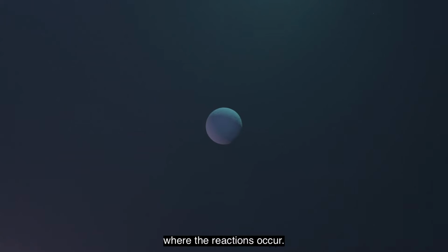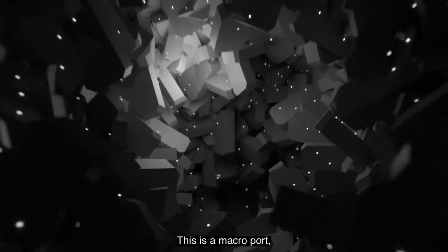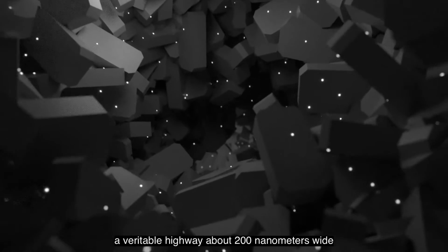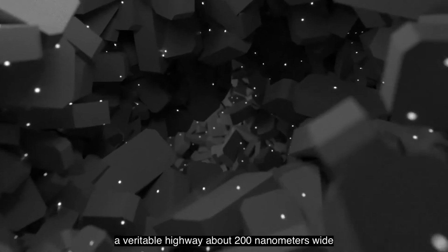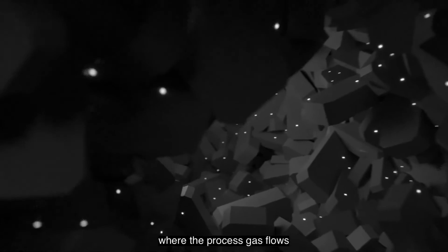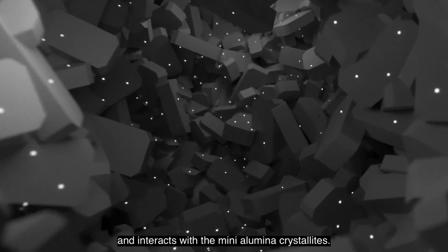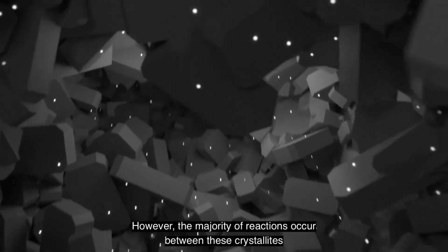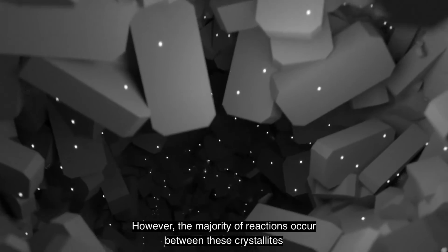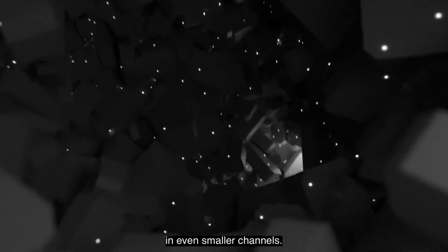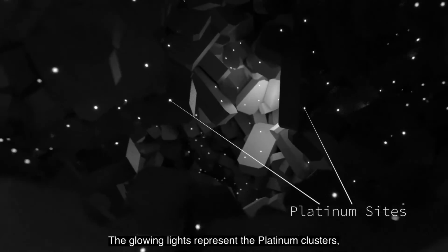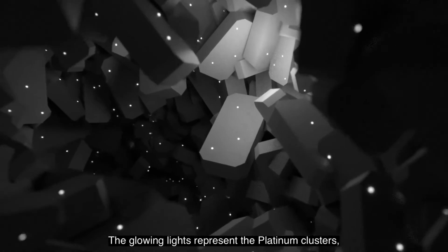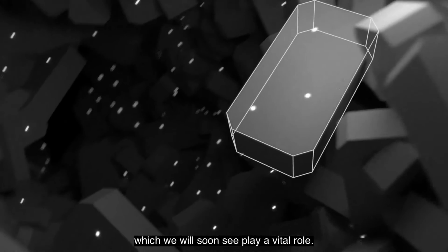To appreciate the chemistry, we need to journey to the atomic scale, into the labyrinth of pores where the reactions occur. This is a macropore, a veritable highway about 200 nanometers wide, where the process gas flows and interacts with the many alumina crystallites. However, the majority of reactions occur between these crystallites in even smaller channels. The glowing lights represent the platinum clusters, which we will soon see play a vital role.